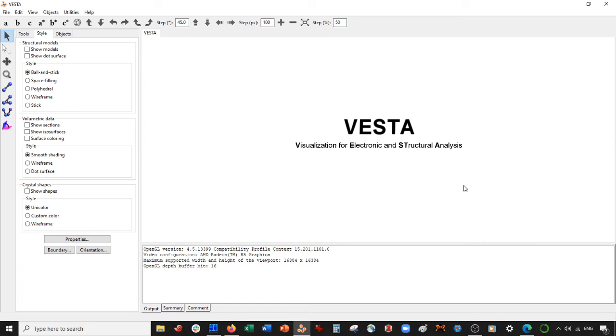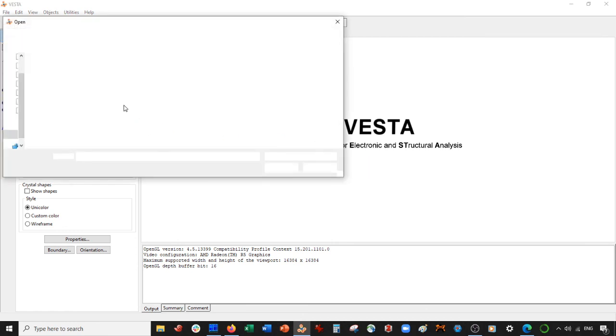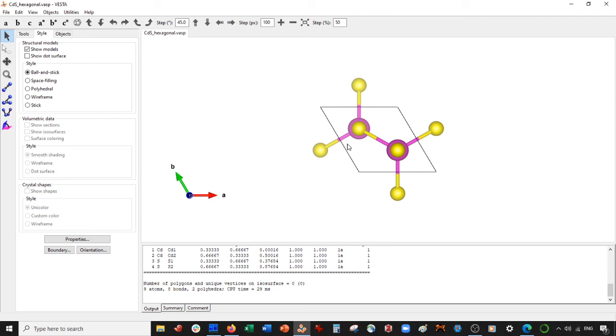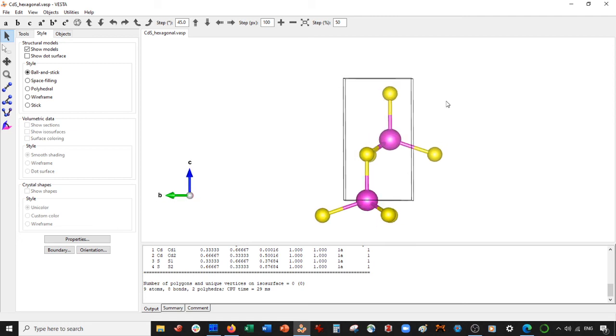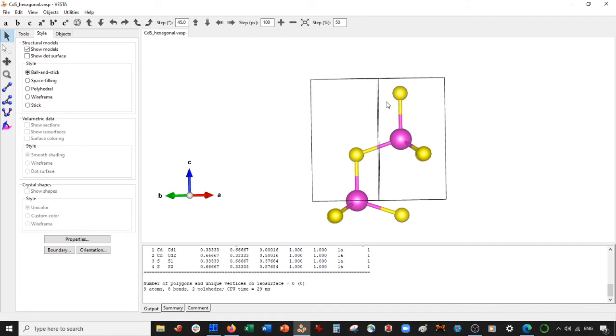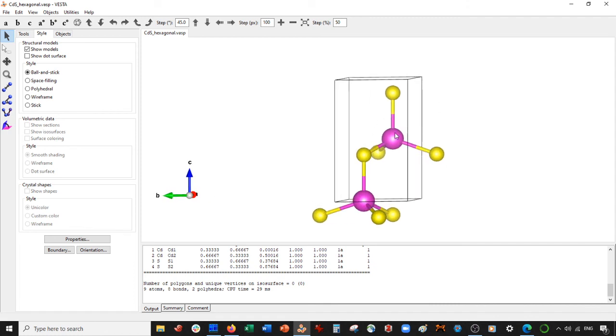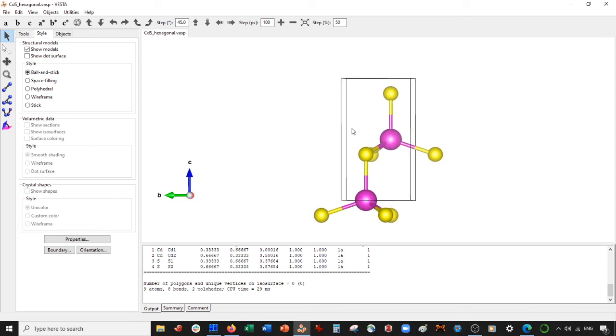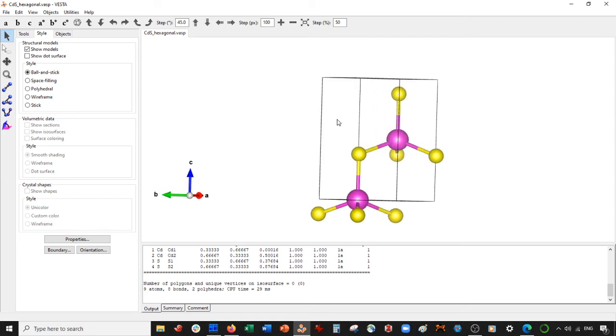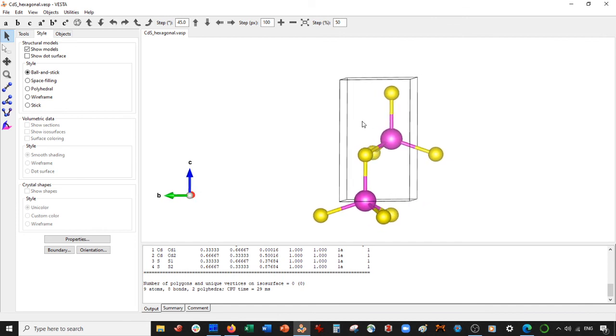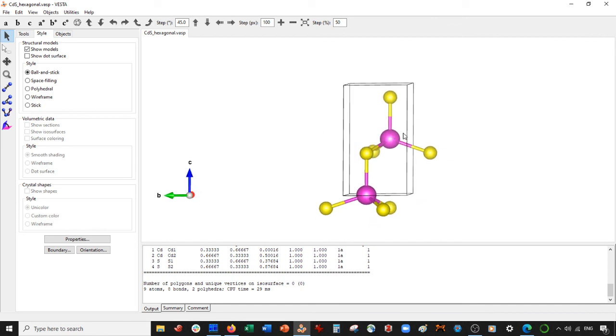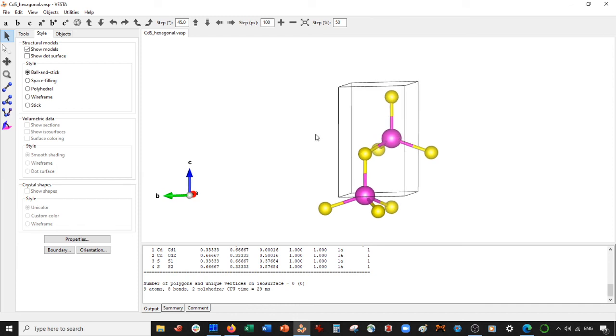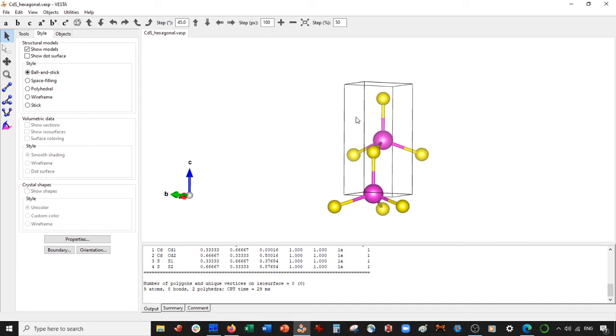Today we're actually going to be making a quantum dot and putting ligands on it. When you put ligands on a quantum dot you have to know how many ligands to put on, and in order to do that you have to know the amount of excess charge you need to quench. We're going to make a cadmium sulfide quantum dot. In a previous video I made a cadmium selenide quantum dot that had a lot of extra cadmium atoms, needing 20+ ligands. Here we'll make a smaller quantum dot with a smaller excess charge, but it will equally show the concept.